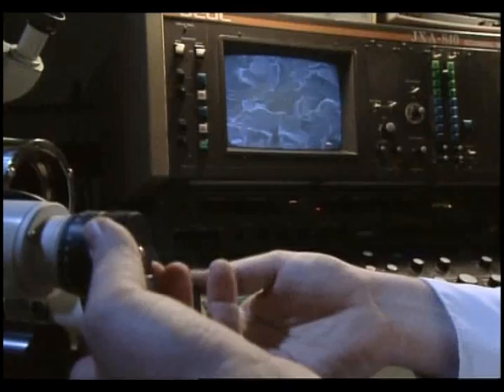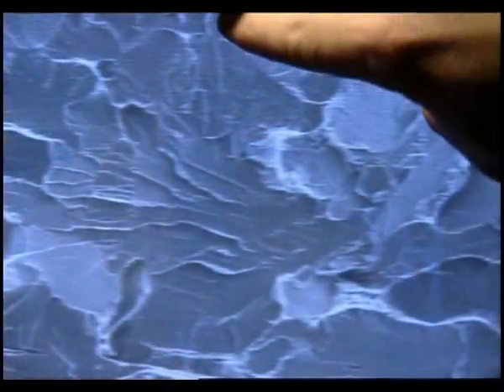The fracture surface shows 95% of the grains in the sample cracked. The lines of the fracture trace back to the weak spots in almost every case. So you see the effect of manganese sulfide particles on the fracture behavior of this steel. More or less, when you take the steel down to a lower temperature, you're actually shattering something that's just full of holes. The night of the disaster, as Titanic begins to break, it's likely that much of the ship's steel suffered brittle fracture. This new evidence supports what some survivors heard.